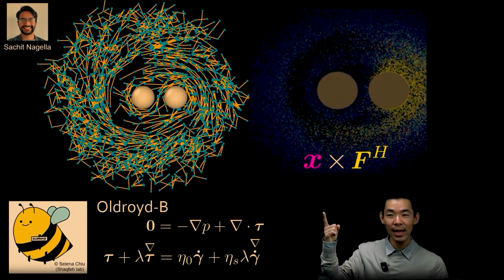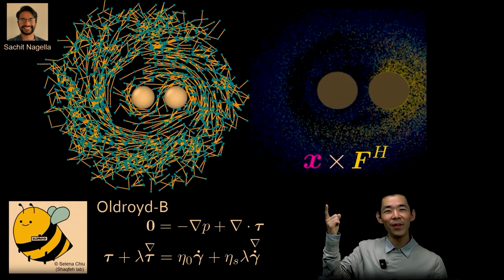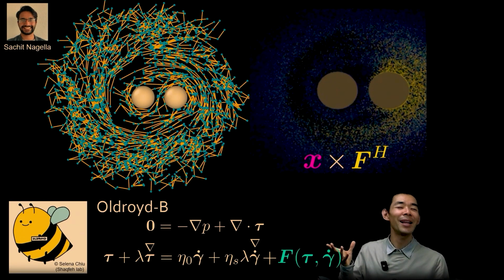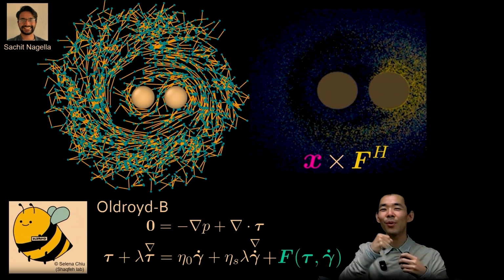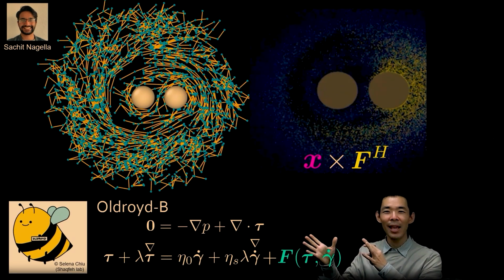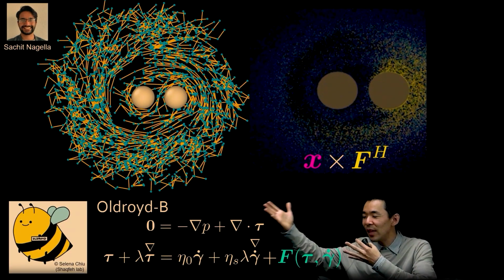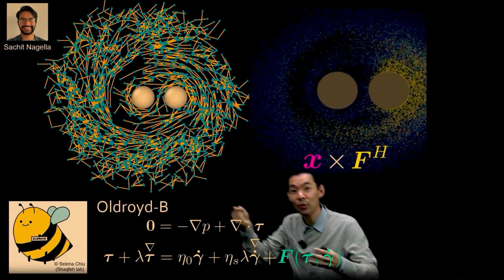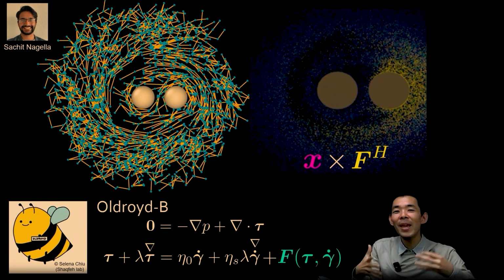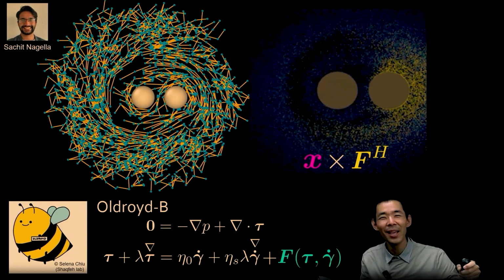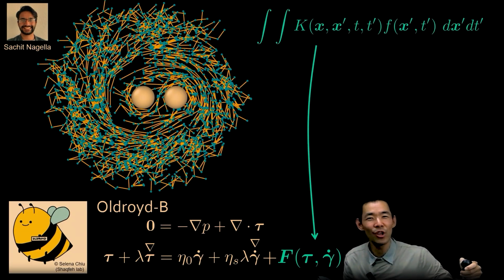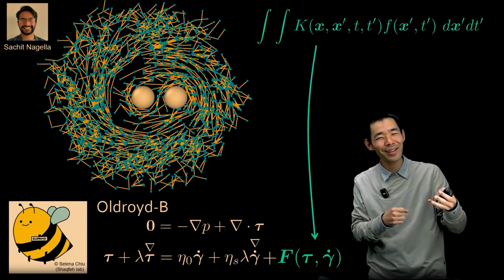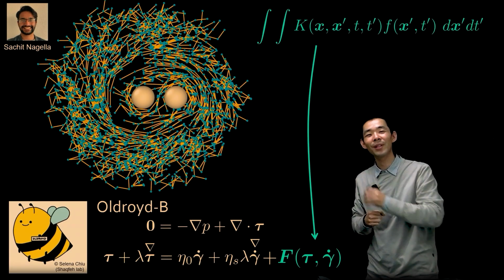Finally, this Oldroyd-B model clearly is missing things. It's missing the inhomogeneity, it's missing local velocity gradients, it's missing the continuum approximation breakdown. So there is a term that encodes all the nonlinearities, the breakdown of the continuum, all here. And until we can develop a field equation that looks just like this and move away from discrete simulations and come to a field equation like this, we can't make much progress in a problem like this. It would be great if we can have a good expression for this unknown term that encodes all the nonlinearities that we're now missing in simple constitutive relations.